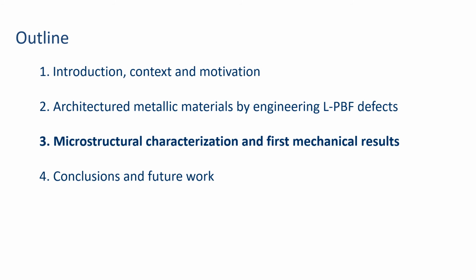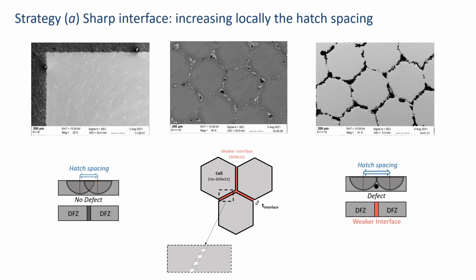So now I'm going to show you a few microstructural characterizations for these two strategies and also the first mechanical results that we have on these specimens. For the first strategy of sharp interfaces, we have been able to find a good compromise between hatch spacing too small, which introduces defects, and you don't see any defect like here, or hatch spacing too large, in such a way that it's not even a defect anymore, but cells which are not really connected to each other and would lead to very bad mechanical properties. And in some cases we were able to generate interfaces that consist of ligaments connecting the cells. However, these good structures have been produced only very recently. I'm not going to show you any more results on this strategy for today.